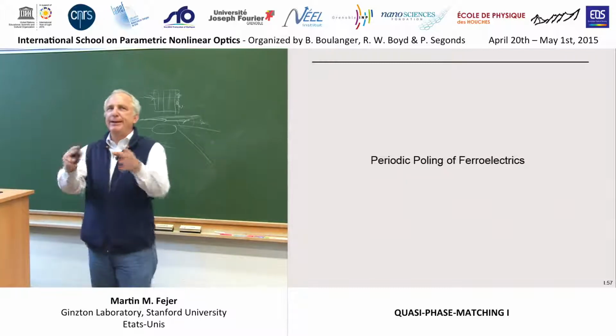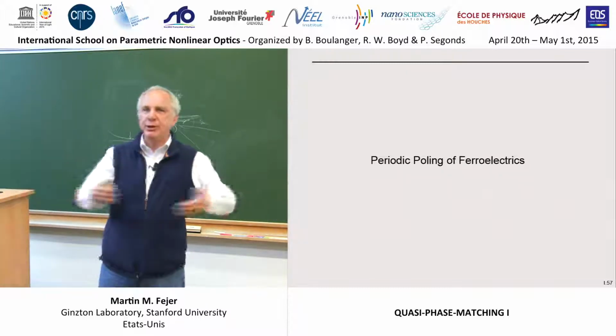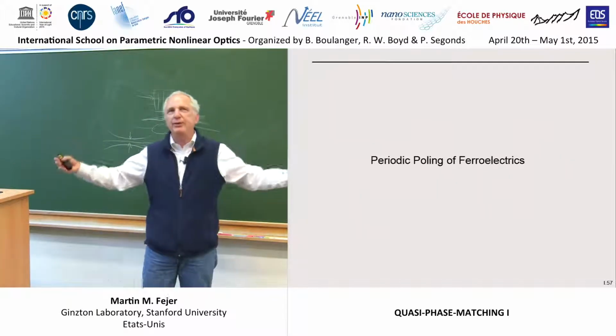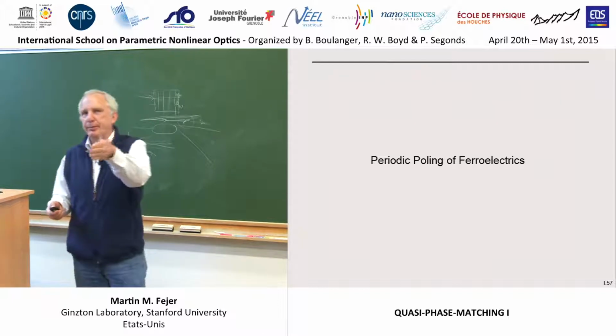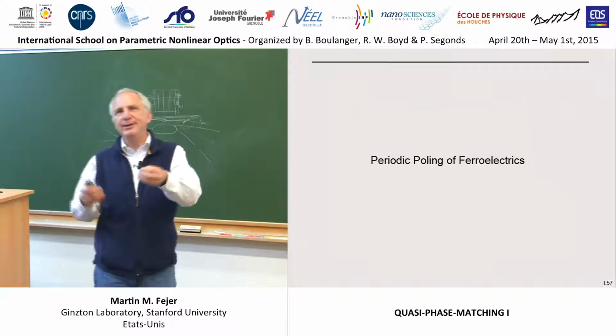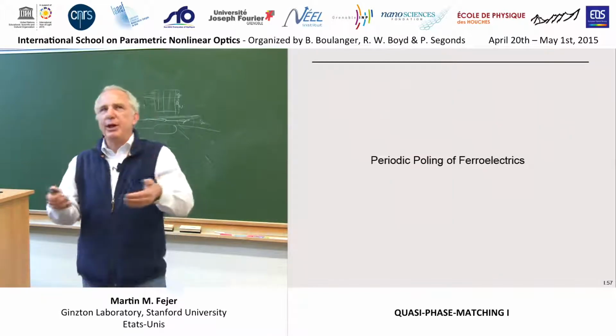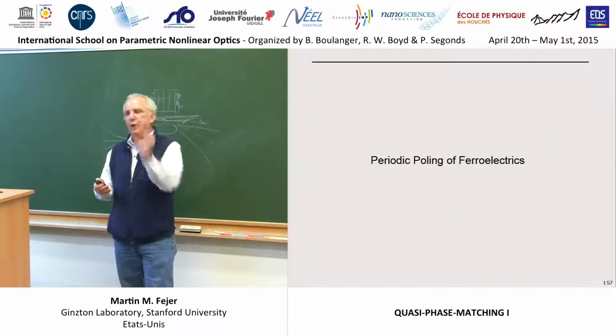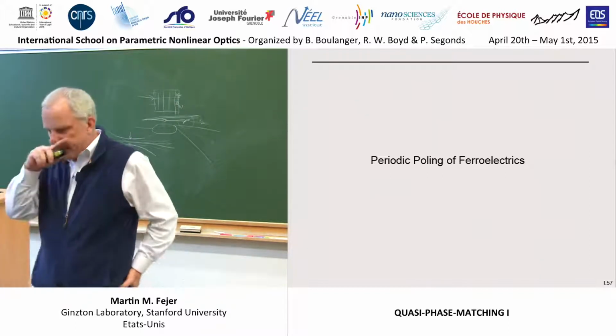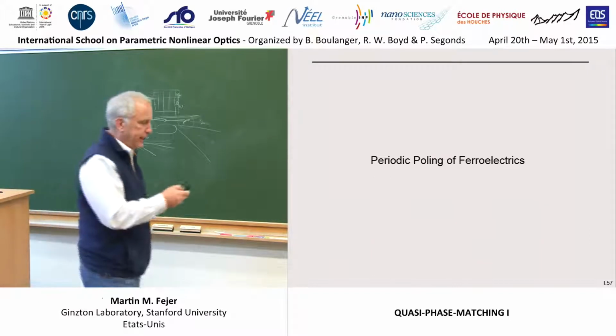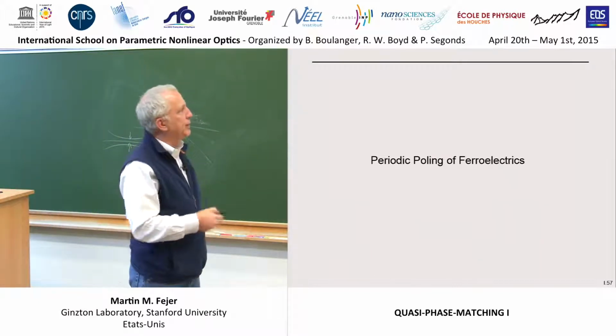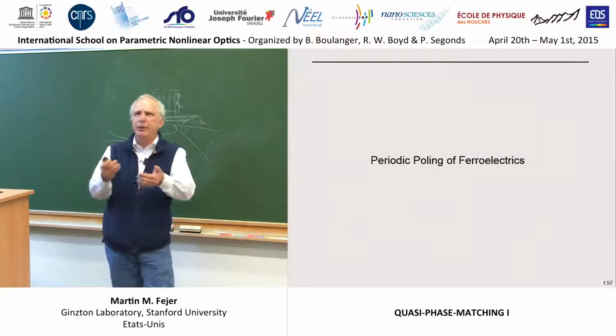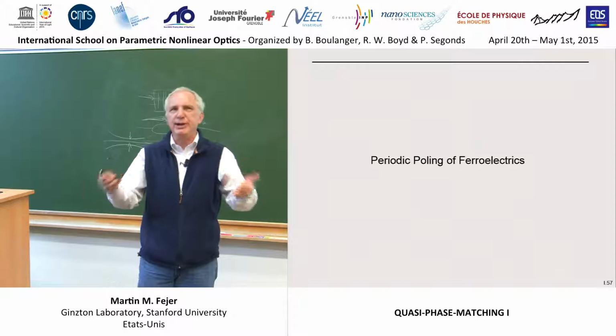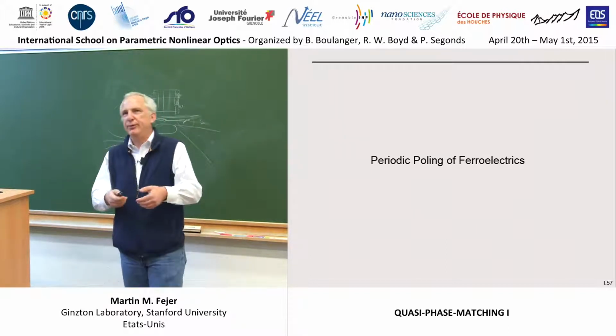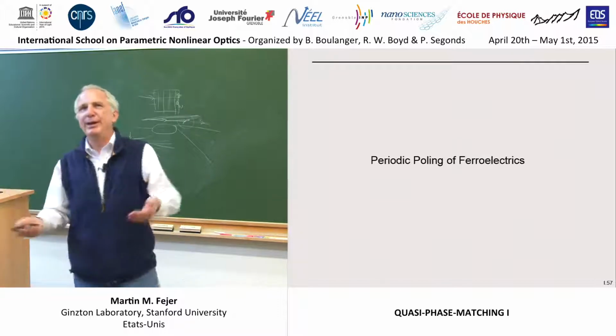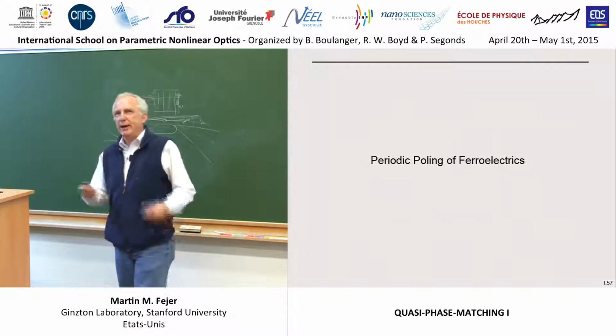So we now have some idea of the kind of periods we need to impose on these crystals, somewhere between a few microns and a few tens of microns, and that we want the accuracy of the domain sizes to be maybe not worse than 10% or so of the width of the domains, so submicron in some cases. So that poses a fabrication challenge, and while I'm not going to try to teach you the details of how to periodically pole ferroelectrics, it's worth knowing a little bit how the process works so you're aware of the kind of errors that can creep in. And when you're trying to convince your vendor to do something he or she has not done before, a little bit of knowledge can go a long way to make you sound like you know what you're talking about.